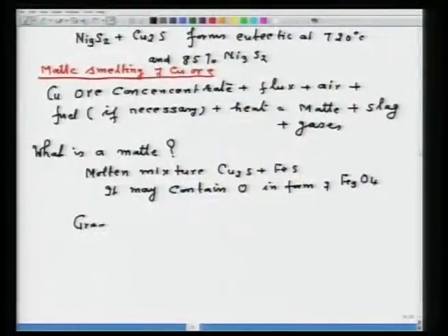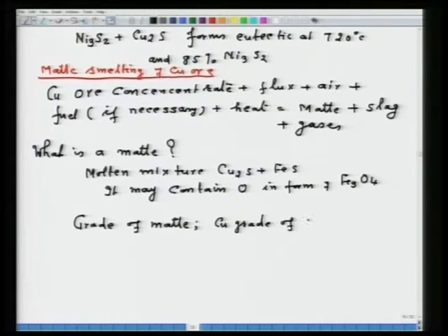Now, an important thing in the case of matte is to define the grade of the matte. Matte grade, or you can also call it the copper grade of matte. It is useless to call it the iron grade of the matte, because you are not concerned with the iron. So that is why you call it the copper grade, that means how much copper is there. If you say you are producing a matte of 40%, that means its copper grade is 40%. So matte is always given in terms of copper, because it is used to produce copper, not iron. So remember, the problem may have 40% matte, or the grade of matte is 40%, or the copper grade of the matte is 40%; all have the same meaning.